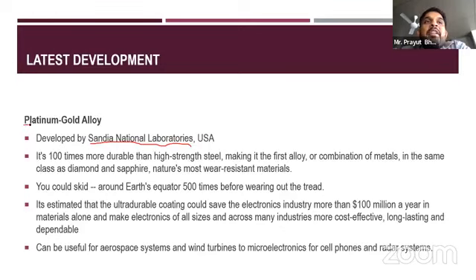Apparently, they developed a platinum gold alloy. Basically, this is a very popular alloy as such. It's already been made, but they modified certain characteristics, the matrix of it, in such a way that it's 100 times more durable than high strength steel. It's making it the first alloy, or combination of metals, in the same class as diamond and sapphire. So these are nature's most wear resistant materials, and they have achieved these properties of diamond and sapphire with the platinum gold alloy.